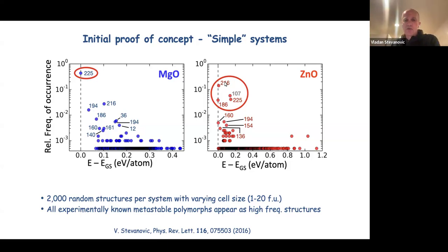In the case of zinc oxide, what you find is the group of 4 structures that occur more frequently than the rest, separated by about a factor of 10, so an order of magnitude in occurrence, from like 3-4% all the way to about 11%, whereas everything else is half a percent or less. So there is a clear distinction in these two systems between low occurring and high occurring structures.